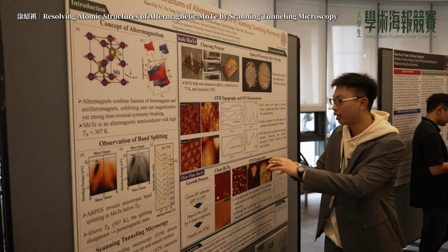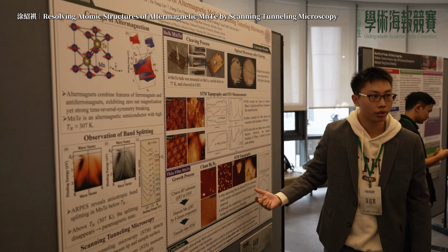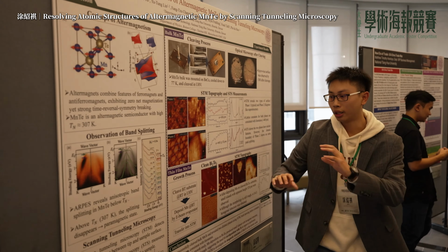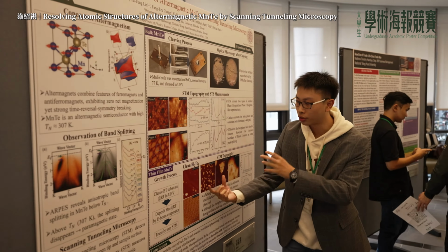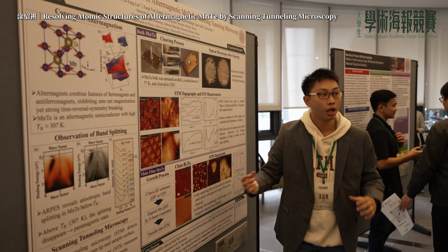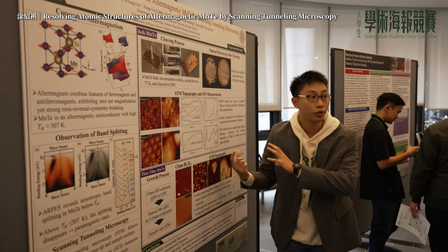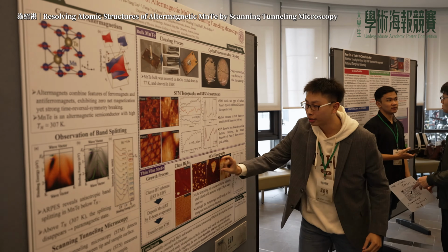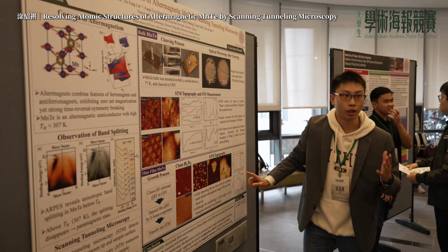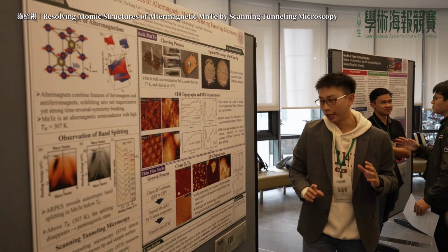And here are the STM topography results after depositing. There are small MnTe islands formed on the Bi2Te3 surface, and the apparent height of the islands is 528 picometers.